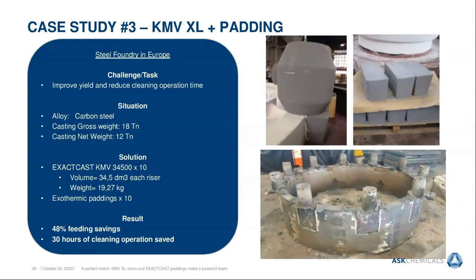In this third case study, we show you the combination of the KMV XL risers together with the paddings. This trial was made in another steel foundry in Europe. This one was a low carbon steel casting with a gross weight of 18 tons. Again, here they have 10 positions of risers, and those risers were a KMV 34,500. This means that each riser had 34.5 liters of metal.